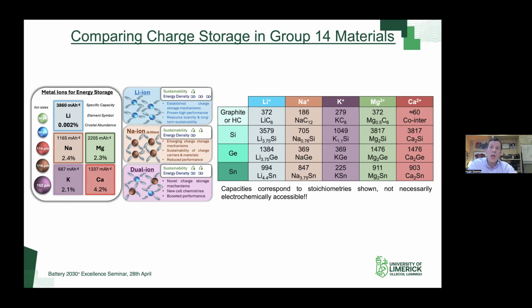What I'll show in the final section of the talk today is around the idea of dual ion batteries. So the idea here is that you would essentially base this almost around a sodium ion chemistry. And what you would do is incorporate some charge capacity boosters into the electrolyte. So the idea here within a dual ion system is that you would have an electrolyte component that contains additional lithium ions within the electrolyte. So what that can hopefully do is basically broaden out this table that we see here and allow us to unlock some new charge storage mechanisms and hopefully boost the performance to find a Goldilocks zone in between sustainability and energy density.